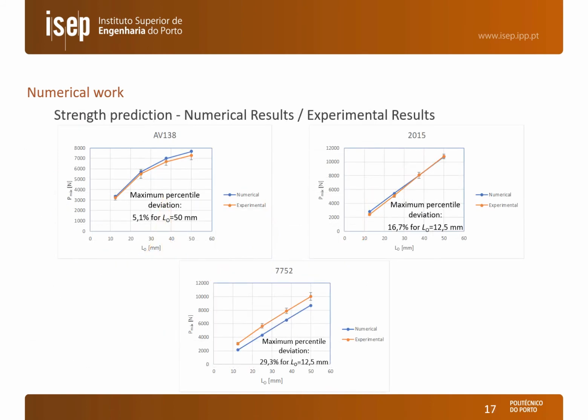Here we can see the comparison between experimental and numerical maximum loads divided by type of adhesive. We can see that we have a good correspondence for the two Araldite adhesives, the AV138 and the 2015. The maximum deviation for the AV138 was 5.1% for an overlap length of 50 millimeters, while for the 2015 the error was almost 17% for 12.5. Opposed to these results, we have higher deviations for the 7752, almost 30%, and this is due to the fact that this adhesive is very ductile and that we are modeling the behavior of this adhesive with a triangular cohesive law.